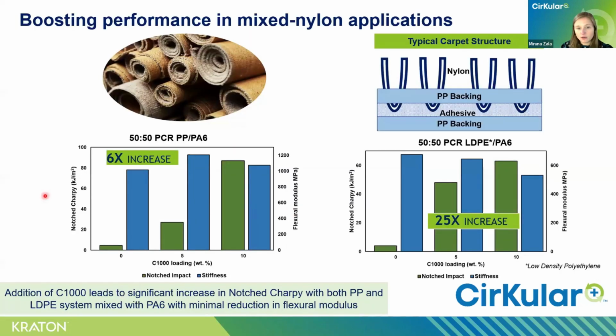So a little bit of data. As you can see here, we are seeing a remarkable effect when we add our C1000 additive. It was added to two different combinations: post-consumer polypropylene and PA6, and LDPE and PA6. In both situations, we are seeing a significant increase in the impact strength. And basically it shows how it can really help boost performance in different polymer blends.